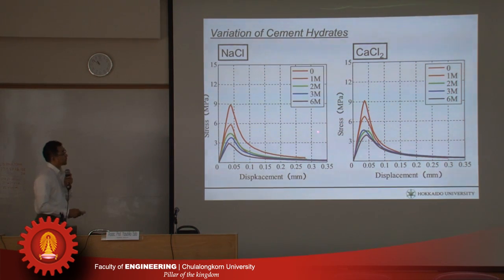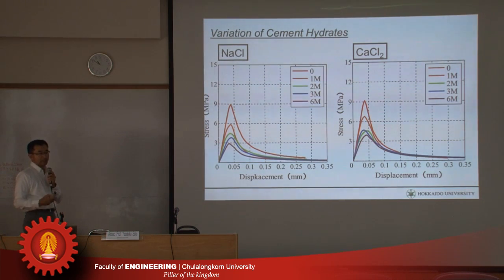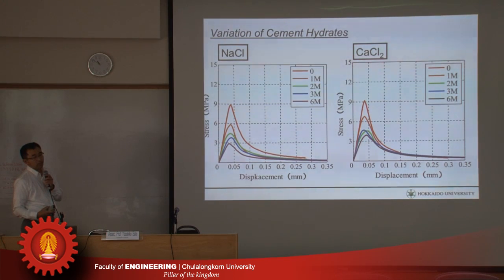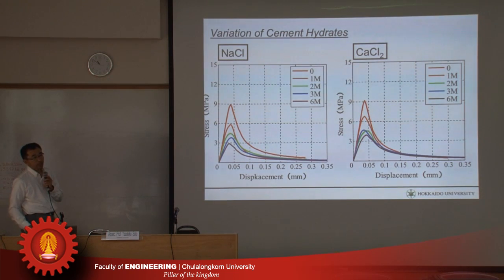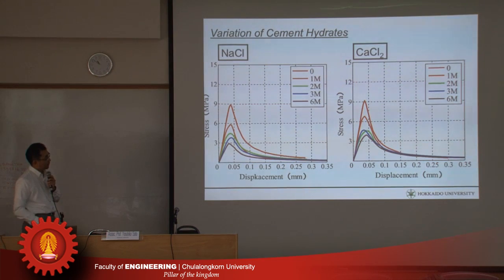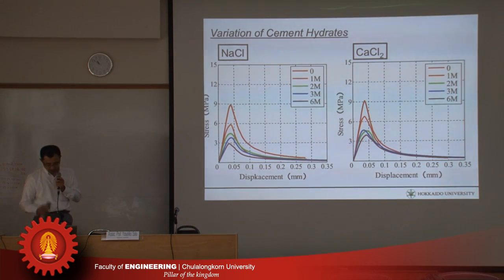In this case, we have a new product — the double salt. Such a newly developed hydrate or compound affects the mechanical properties of the mesoscale specimen. That's why we have to detect how these newly developed ones influence the overall behavior of our specimen. This is one thing.